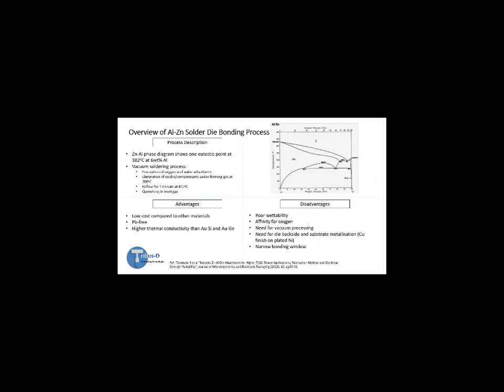The zinc aluminium or aluminium zinc solder die process is a bit of an odd one. There's been a lot of development, particularly in Japan, looking at this as a lower cost alternative to other solders. It's got potential for high temperature operation because the eutectic point is above 380 degrees C. But zinc and aluminium are very active materials. So wettability, affinity for oxygen, need for vacuum processing, how you apply metallization to the die backside and substrate, and controlling that are some of the key areas there. So if you can invest a lot in equipment and handling and complete control of the supply chain, then there's a chance with aluminium zinc soldering, but it's not going to be an immediate replacement for SAC soldering, which you can put through an oven, and it will work pretty much every time.